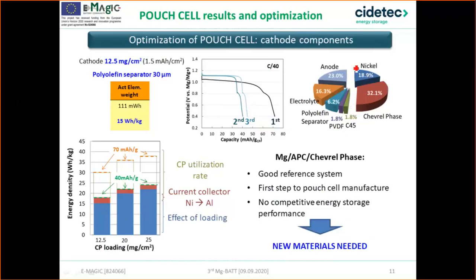Also, analyzing the contribution of other components of the cell, we realize that there is room for improvement. On the one hand, we can improve the Chevrel phase loading in the cathode to improve the energy density. Then, the current collector is nickel in this case, but if we are able to replace the electrolyte by a non-corrosive alternative, and in the frame of the project some partners are working on it, we will be able to replace it by aluminum, and consequently improve the energy density around 5%. Then, if we are capable of delivering higher values of capacity, up to 70 milliampere hour per gram, which is a reasonable value at coin cell level, we will raise the energy density to around 40 watt-hour per kilogram.